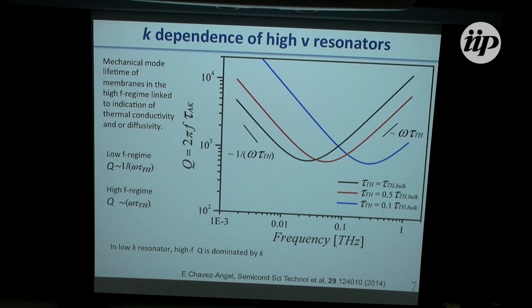Or you could perhaps shift this one here and see that there is a clear dependence of the Q factor of a resonator, the thermal conductivity of which will be diabolic to model because it is a beam with holes, varying periodicities, etc. So we are testing these calculations now and see if, by measuring Q, we can extract perhaps empirically the thermal conductivity without really understanding too much as to the mechanism of it, but at least as a measure, because Q is an indication of how good your resonator is and the kind of losses you have. And we know we have losses due to the thermo-optic effect and carrier density.